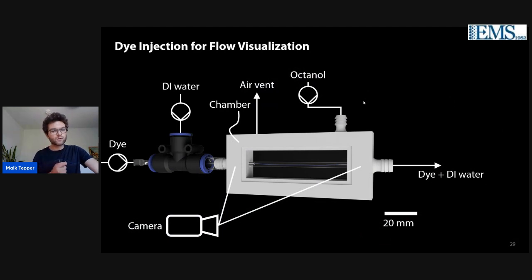And that means once we fill up the pores with a liquid of a very similar refractive index as the membrane material itself, we can make this combined membrane material and the membrane transparent. And apparently octanol has a very similar refractive index as PVDF. So this PVDF membrane swollen in octanol is now transparent. So that means that we can look into the inside of the fiber.